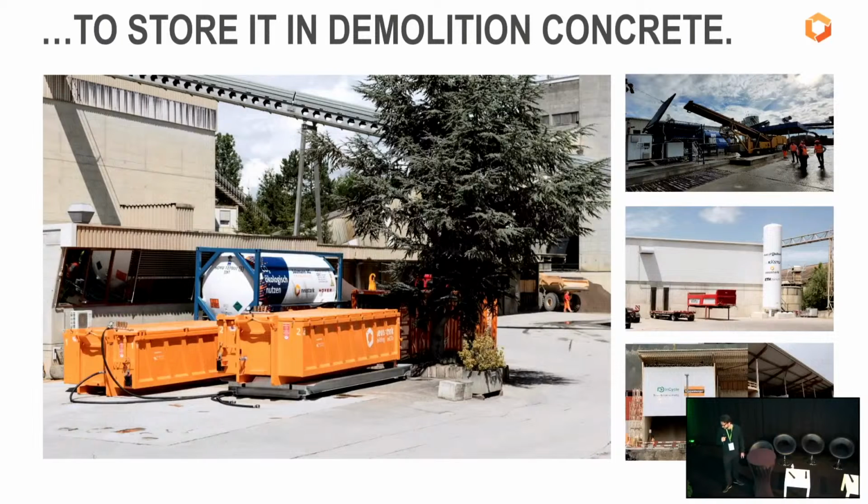What you see here are a few different solutions that we use. Basically, the orange containers you see in the large pictures are some of the mobile containers. They function simply: you open the lid, you load the gravel or the recycled granulates with the wheel loader, you close the lid, you inject carbon for 2 hours, and then you bring the recycled granulates back into the value chain. You see a couple more on the right side. These are more the fixed installations.